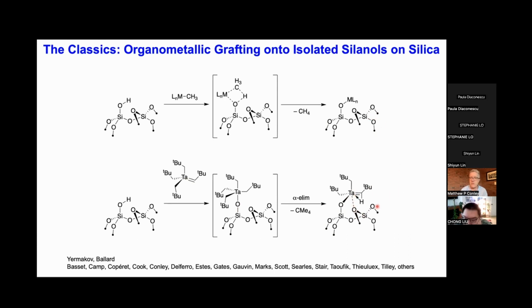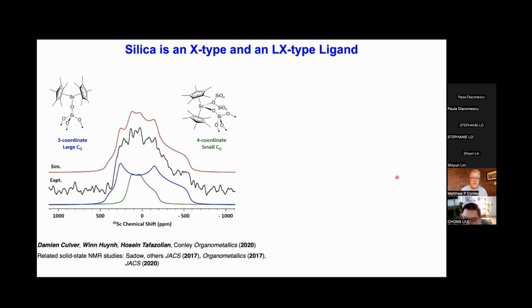It turns out both of these normally happen, and it's dependent on the steric properties of the metal. So one example that we looked at in my group was the reaction of bis Cp* scandium methyl with silica 700. And we chose this because scandium has a really great NMR active nucleus where we could probe the coordination environment with respect to the scandium-45 NMR properties. So I don't want to go into detail about why we see broad lines with scandium, just kind of take my word for it. If you see this experimental spectrum, you can fit this to two different sites.